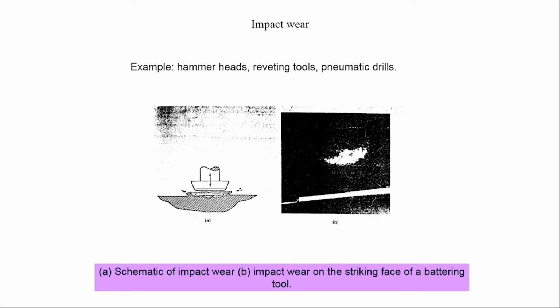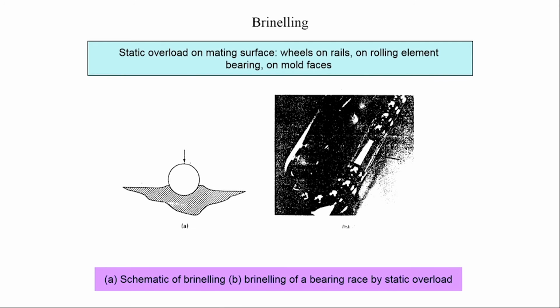of wear, you have to look for the hard facing operation, and for hard facing, different iron, cobalt or nickel based superalloys, the hard faced alloys, are available. So, you apply a typical weld overlaying technique in order to develop the hard faced layer on the surface, and that layer will help the component to avoid that impact wear.